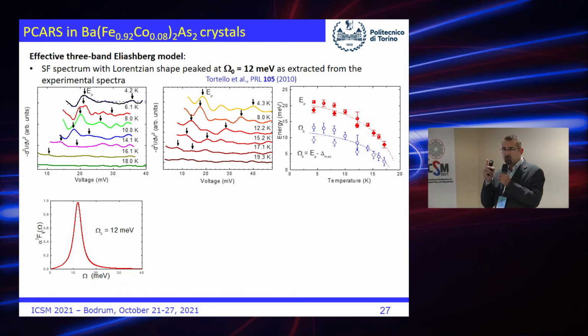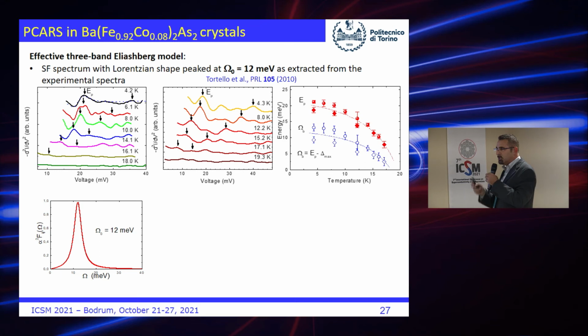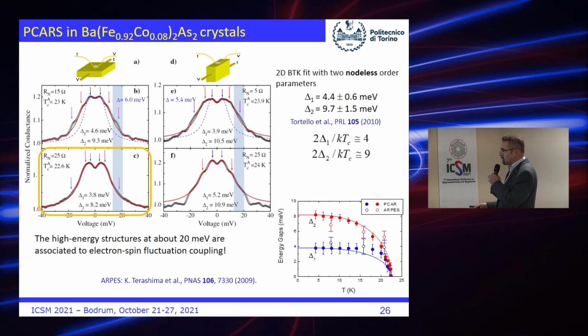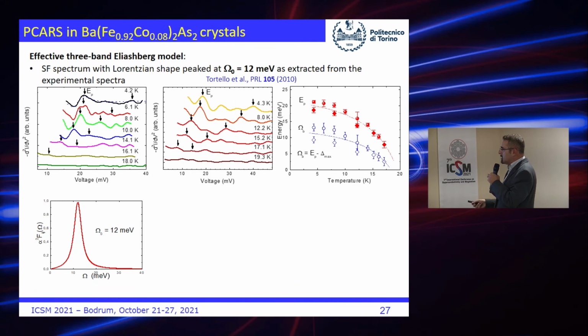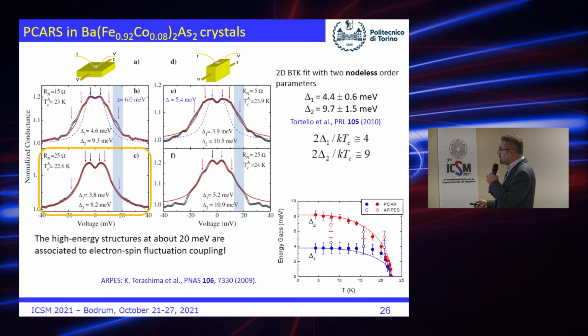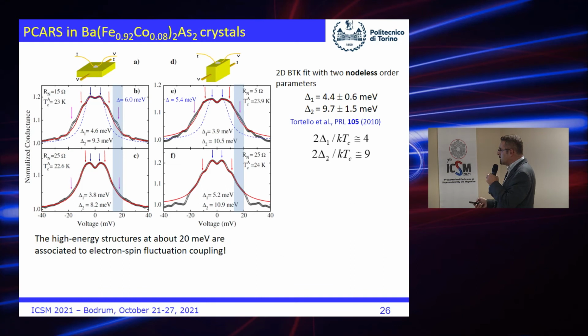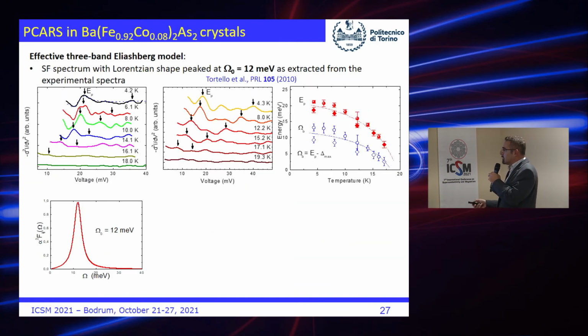So now we do not assume the energy of the boson, but we look directly at the second derivative. This black curve here is the derivative of this. This one is a derivative of another contact. And you look at them, and if you plot the positions of the peak, you obtain these 2 red series